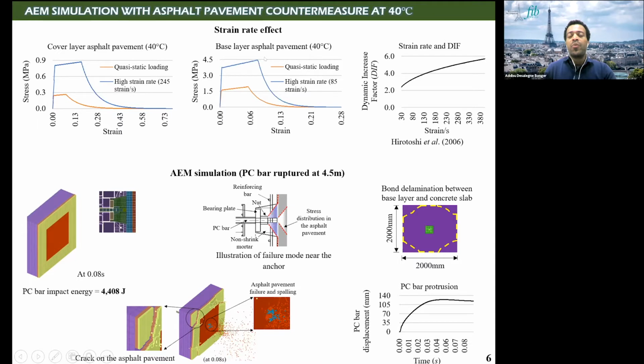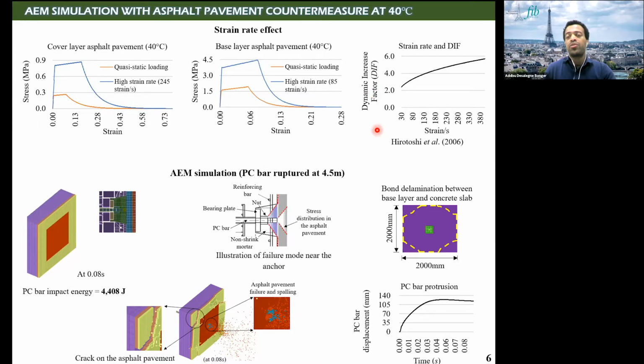Another thing is when the PC bar is impacting the asphalt pavement, the pavement might be fractured under a high loading rate. So it was necessary to consider the effect of a strain rate in the numerical simulation. Several past research also showed that the asphalt pavement and concrete are highly rate dependent. This researcher showed the strain rate with the respective dynamic increase factor.